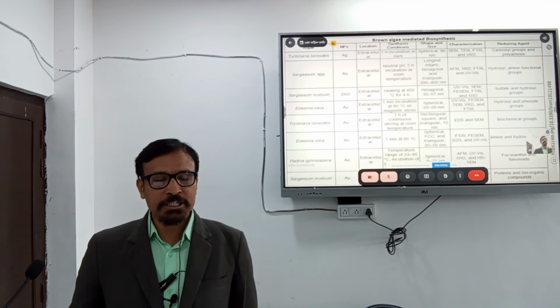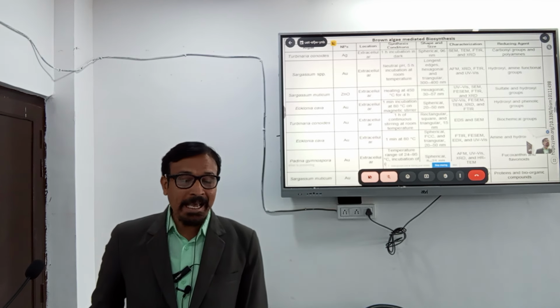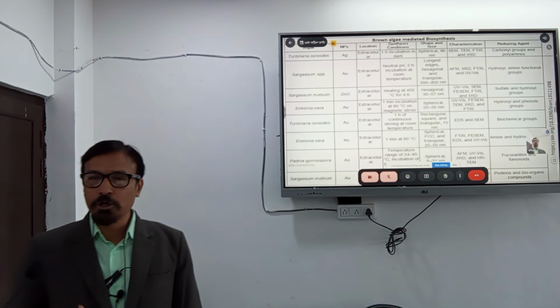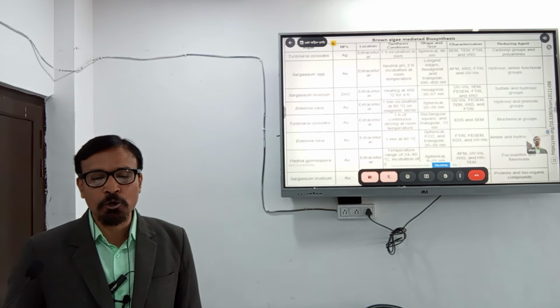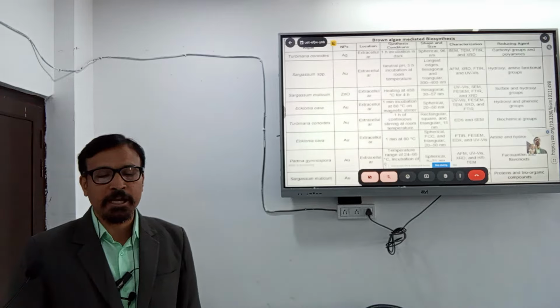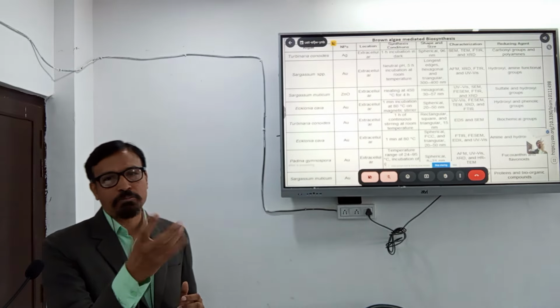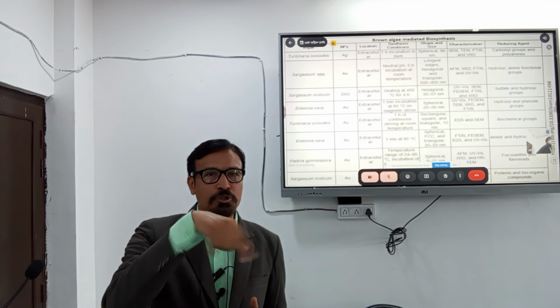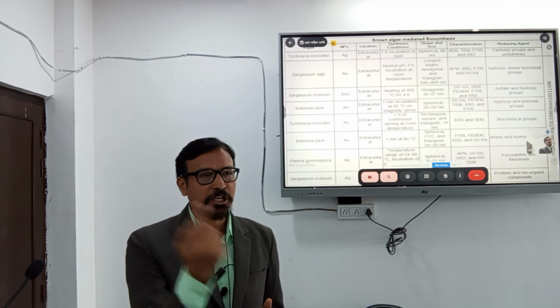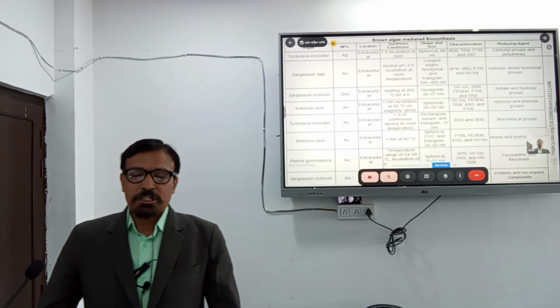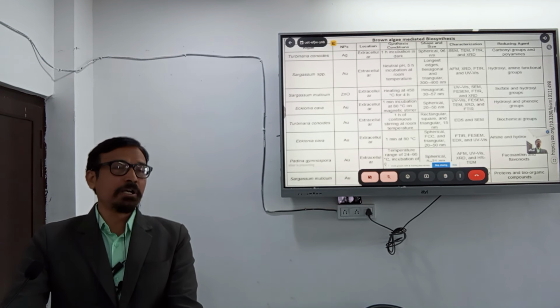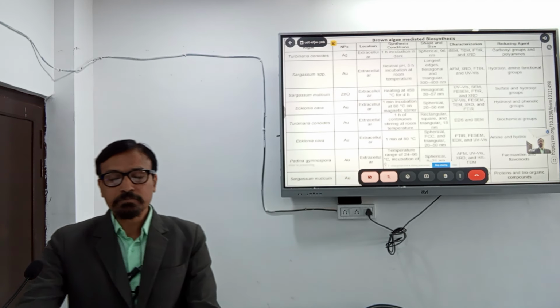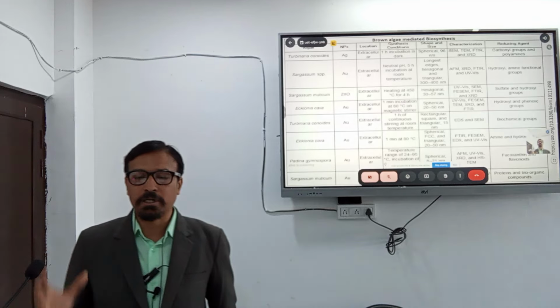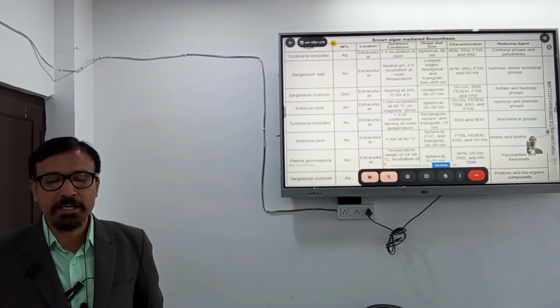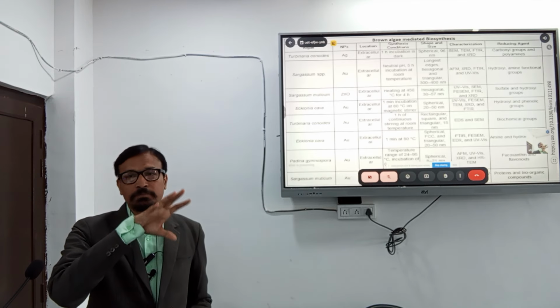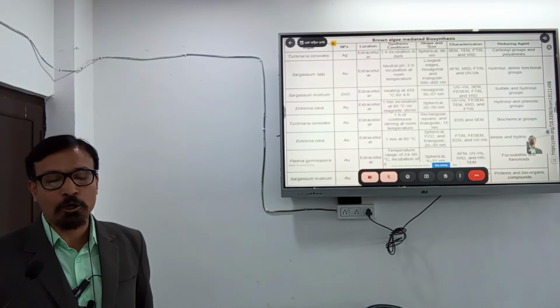And next is Ecklonia cava, which is also an algae, and it can produce gold nanoparticles. The location is also extracellular, and the synthesis condition is 1 minute incubation at 80 degrees Celsius in a magnetic stirrer. So we need the magnetic stirrer for this process, because for many reactions there is a stirring requirement. Spherical nanoparticles will be obtained by Ecklonia cava, and we can characterize them with UV-Vis, FESEM, TEM, XRD, and FTIR. Hydroxyl and phenolic groups are what will reduce the ionic species of the nanoparticles.